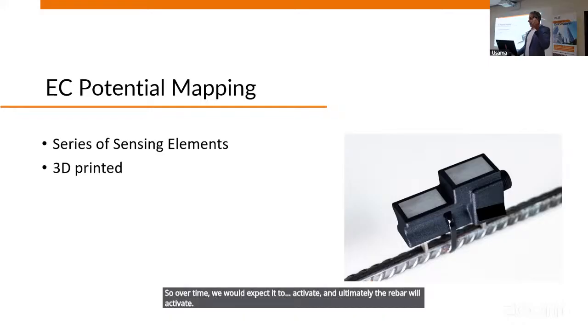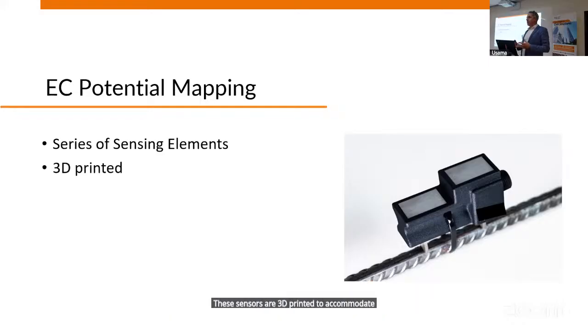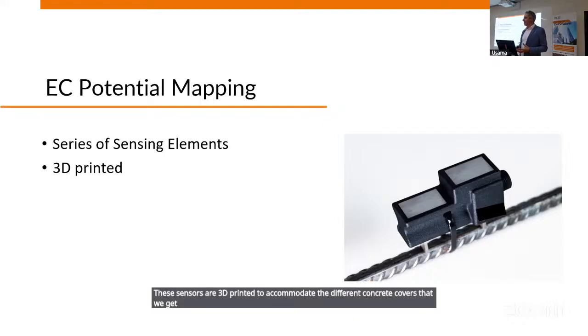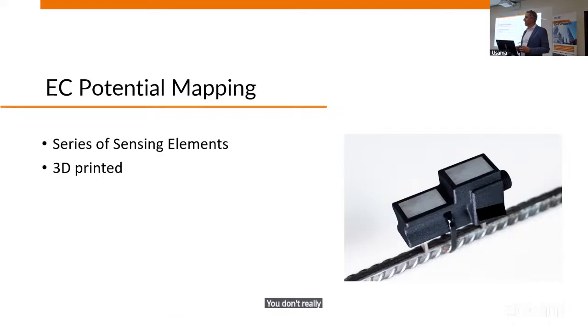These sensors are 3D printed to accommodate the different concrete covers that we get in structural elements. So it could be a 50 mm cover, 75 mm cover. We rarely go down below 50 mm. If it's below 50 mm, most likely the environment is not corrosive, and you don't really need to be monitoring for corrosion. But it can be customized to meet the structural element that's in question.